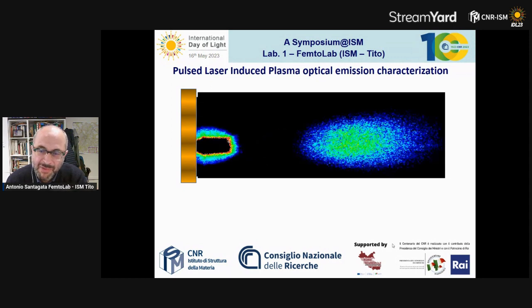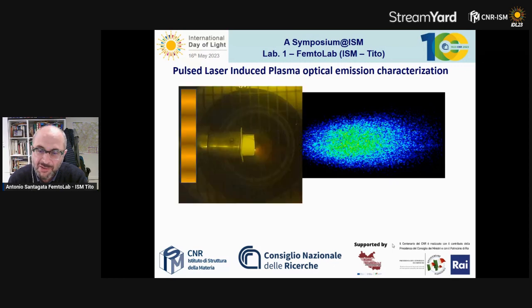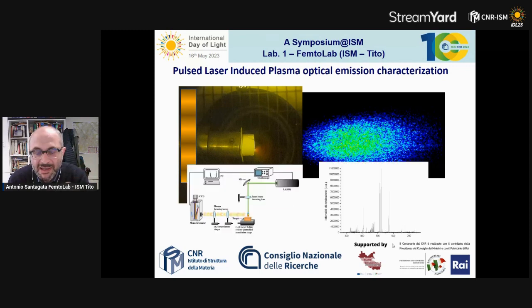which by using femtosecond sources is actually formed by two components. One, ionic and atomic species, which are much faster than the second part, which is made of nanoparticles. The emission of the plasma induced by laser can even be used for analytical detection of the excited species. And so we use this kind of feature for laser-induced breakdown spectroscopy, for characterizing materials.